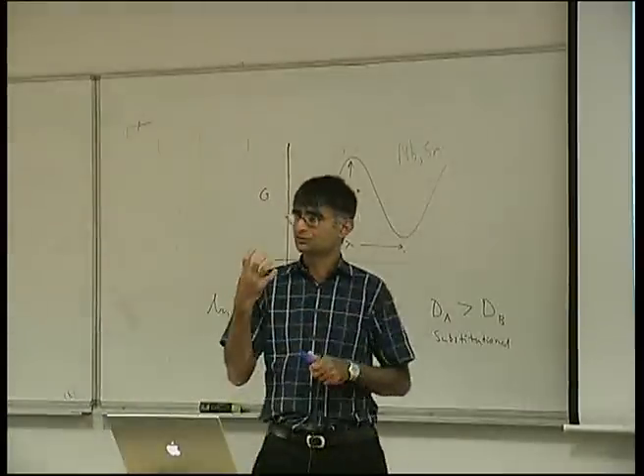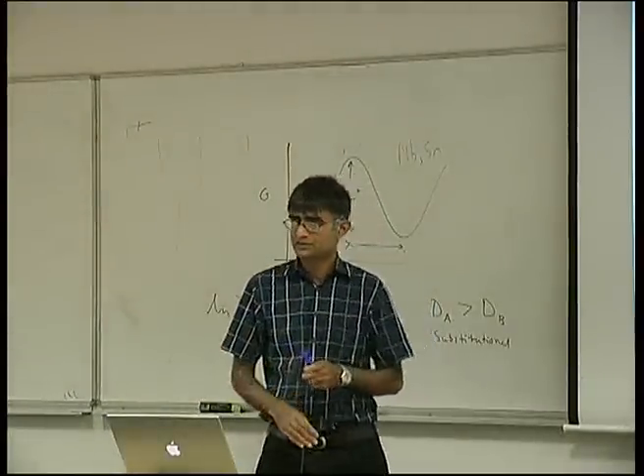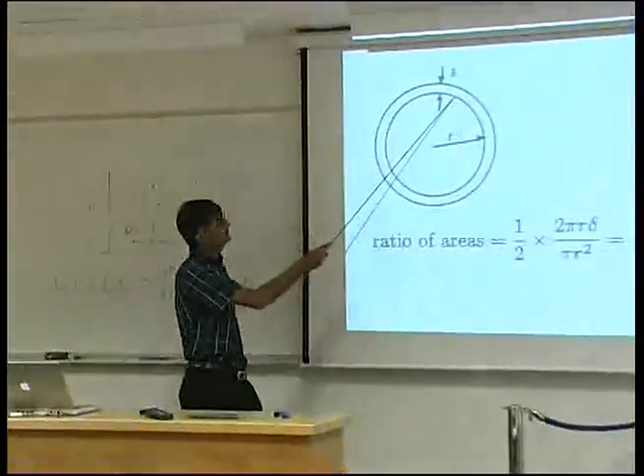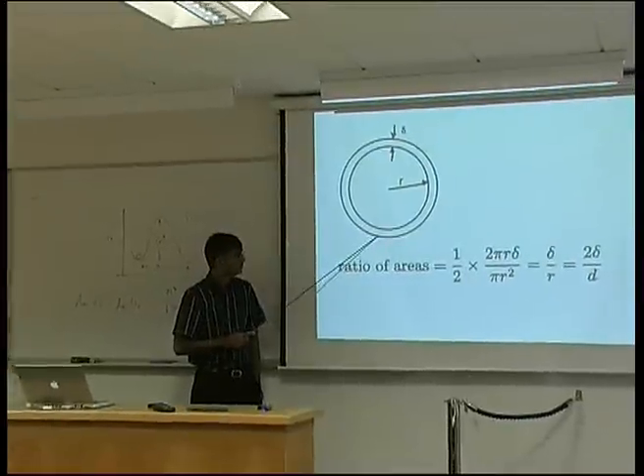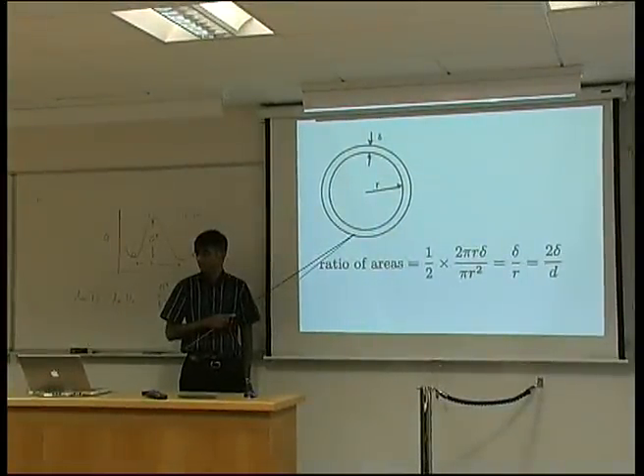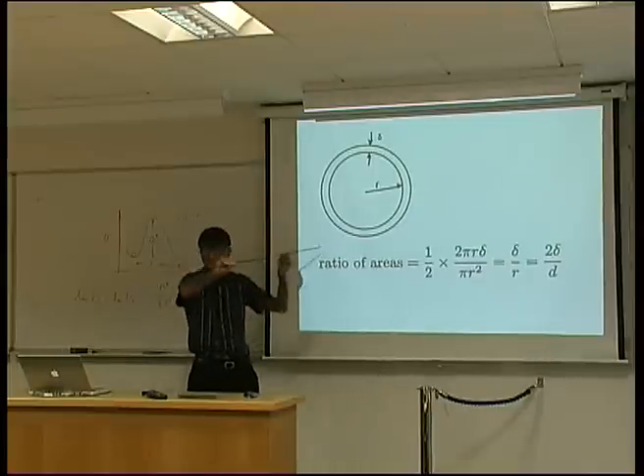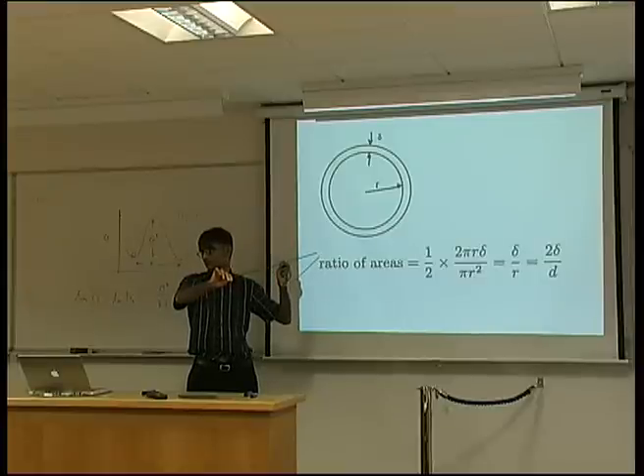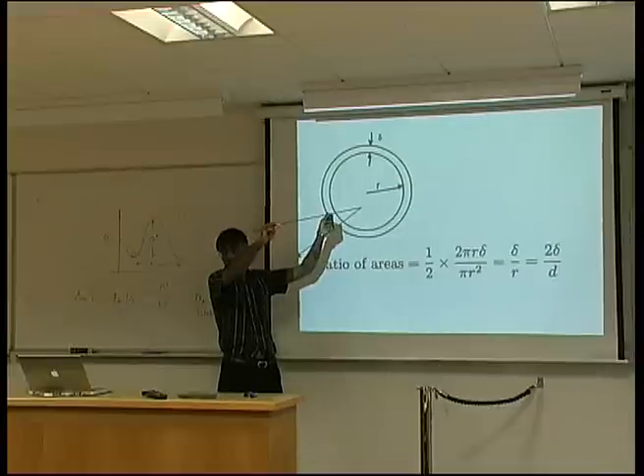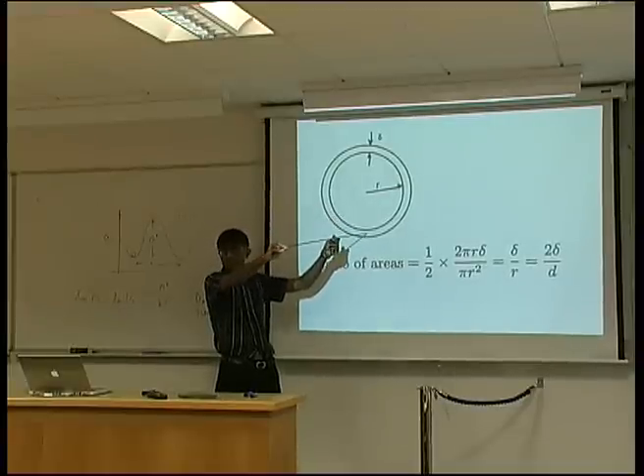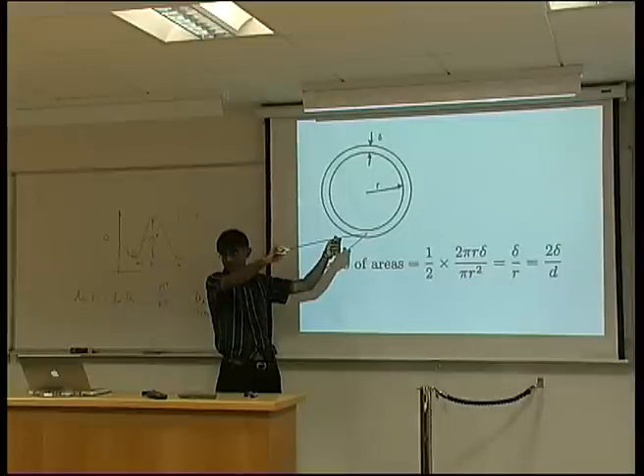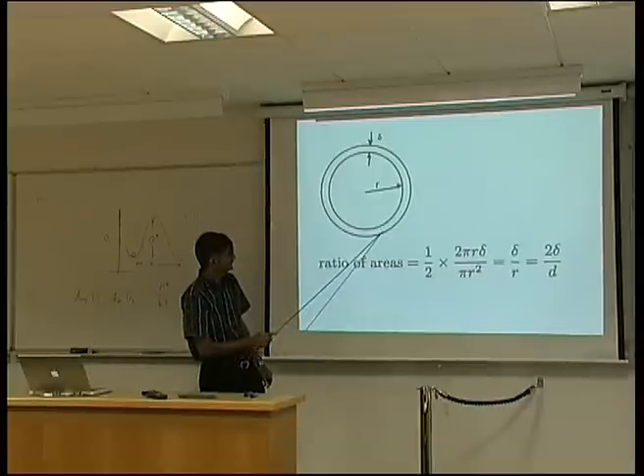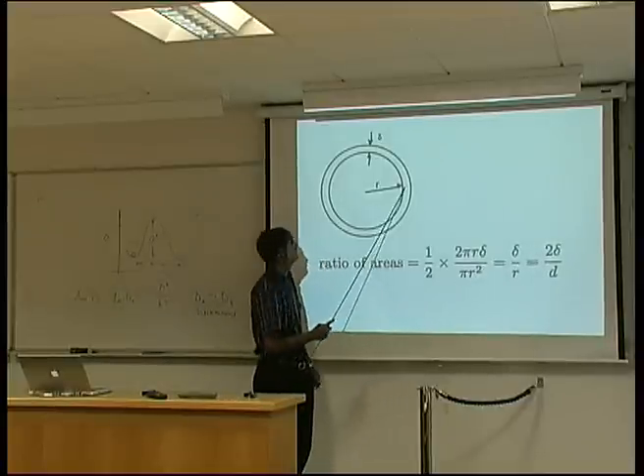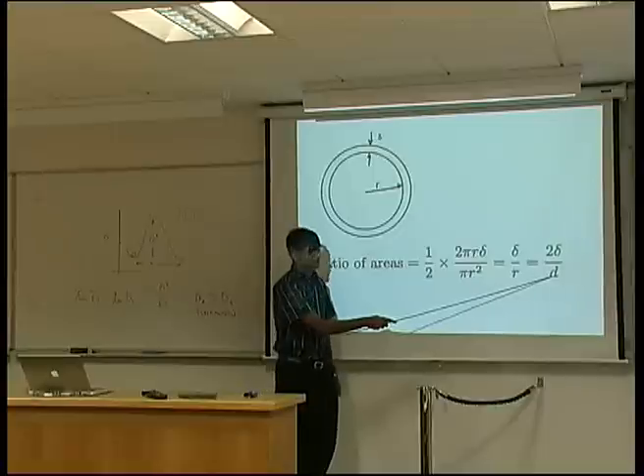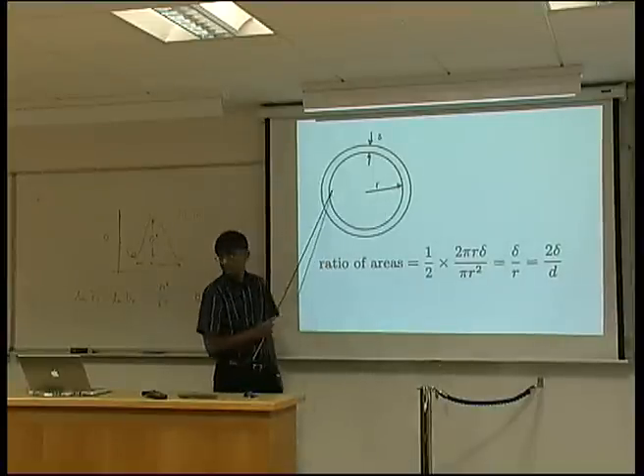So we need to think about structure-sensitive diffusion. That means that supposing this much of my material is perfectly crystalline, but I have this much of it which is defective and has a much higher diffusion coefficient, then clearly the flux in this direction is going to be greater than I expect. Because obviously flux is going in through the perfect material, but it'll be going in faster through the defective material. And the fraction of defective material from simple geometry is the thickness of this region, 2 delta, divided by the diameter of this region.